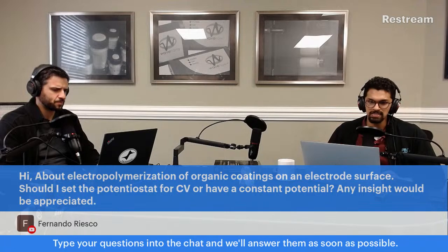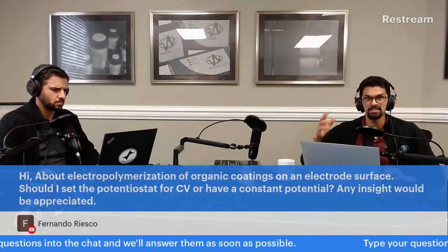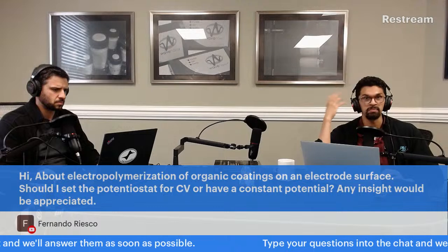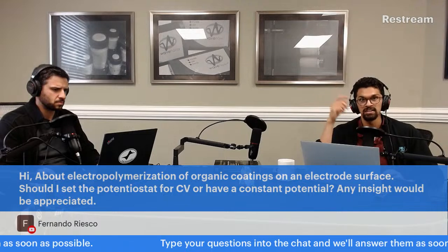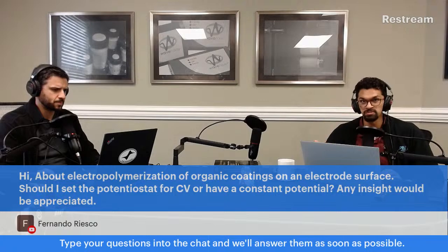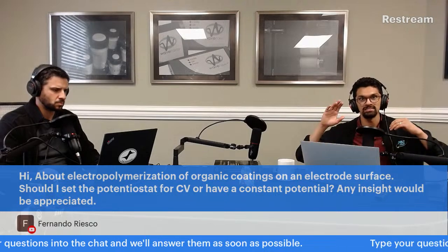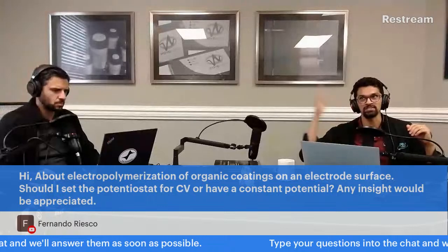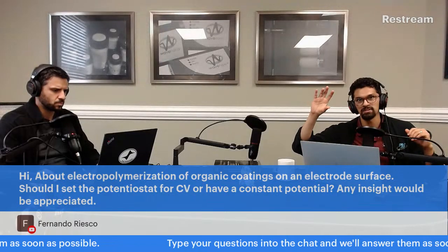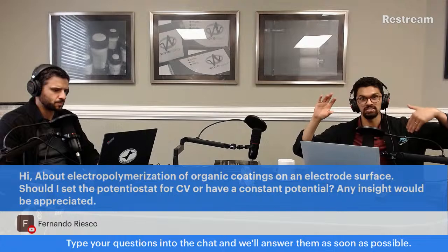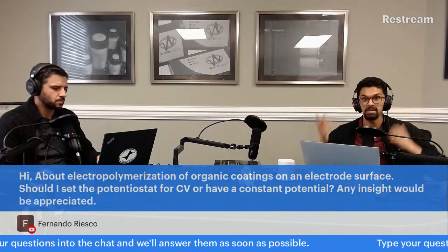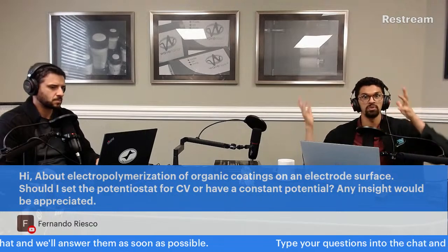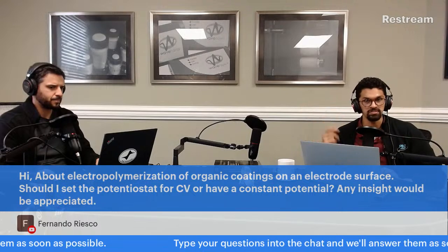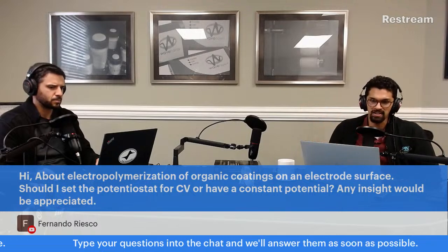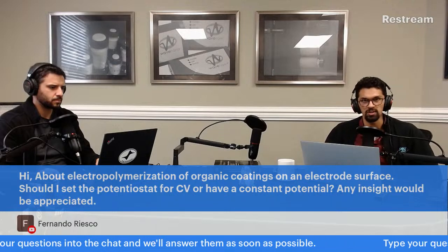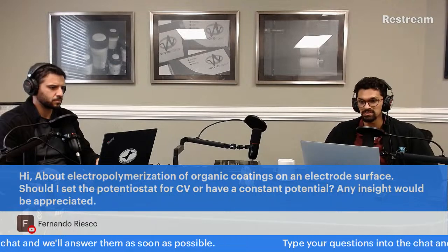The only thing to keep in mind with CV is you might remove the polymer coating off of the surface if you're cycling back and forth, but you would observe that by seeing the opposite peak. So if you have an oxidation to form the polymer, and then you start seeing this reduction reaction occur, then maybe that is removing or destroying the polymer, or vice versa. So that's my advice for starting off. I'd start with CV and maybe even do a few cycles of CV.